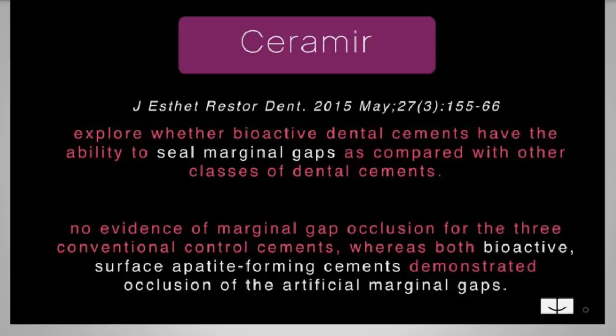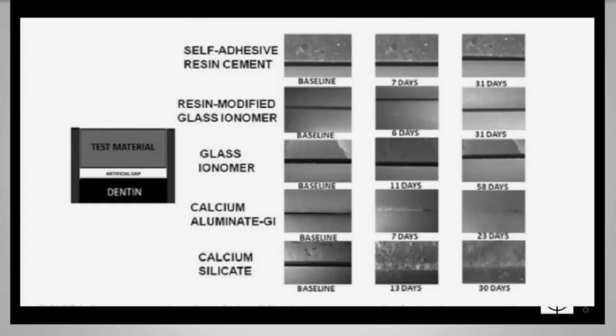So here is a study. It just came out in May. It's absolutely amazing. And what it shows is whether or not bioactive dental cements have the ability to seal marginal gaps as compared with other dental cements. They basically found that bioactive surface apatite forming cements demonstrated that you could actually occlude artificial marginal gaps. So we all know that our crowns don't fit perfectly, right? There's always some gap there. No matter how good, how accurate our crowns are, there's always a little bit of a gap.